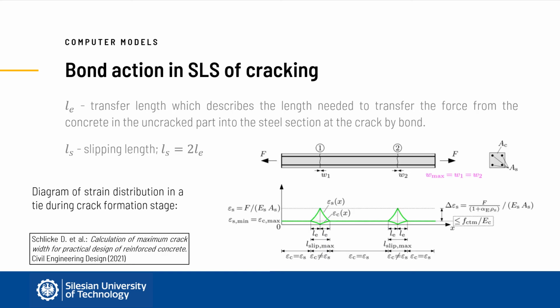Let us imagine the case of a tie in a crack formation stage. The absolute displacements of steel and of concrete along the transmission length are different. This relative displacement generates bond stresses between concrete and steel. Along the transmission length, a part of the tension force of the reinforcing steel, which is acting in the crack, is transferred into the concrete by bond. This effect is called tension stiffening.